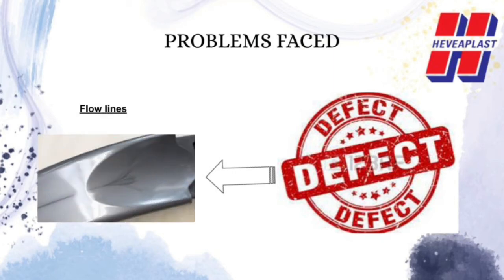The last one is flow lines. Flow lines are streaks, patterns, or lines that show up on the prototype part as a consequence of the physical path and cooling profile of the molten plastic as it flows into the injection mold tooling cavity. Usually, flow line defects are caused by the varying speed at which the molten plastic flows as it changes direction through the contours and bends inside the mold tool. They also occur when the plastic flows through sections with varying wall thickness or when the injection speed is too low, causing the plastic to solidify at different speeds.